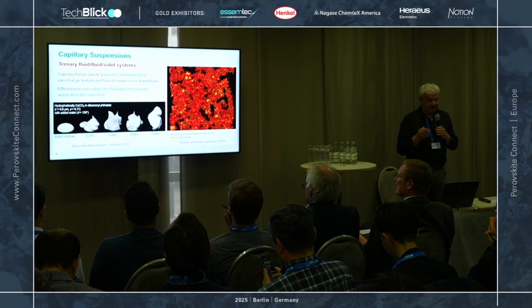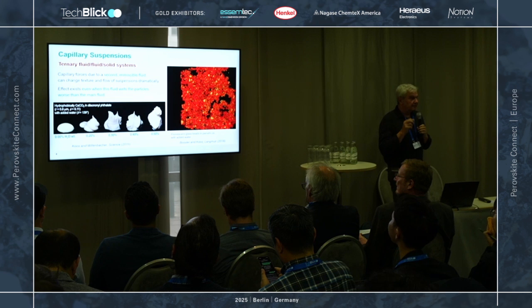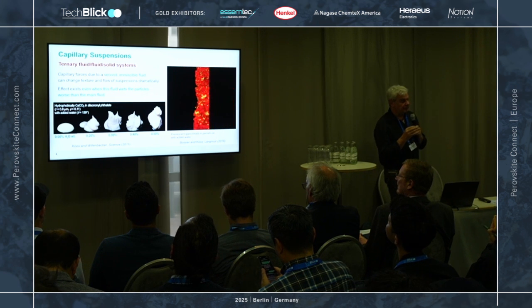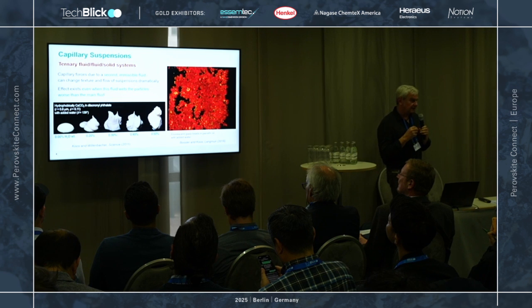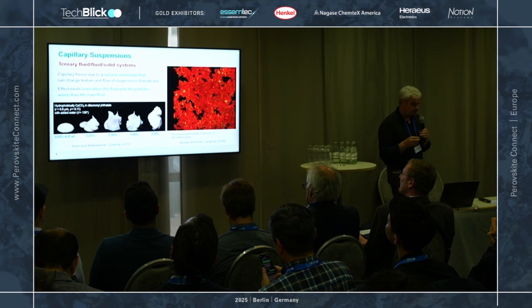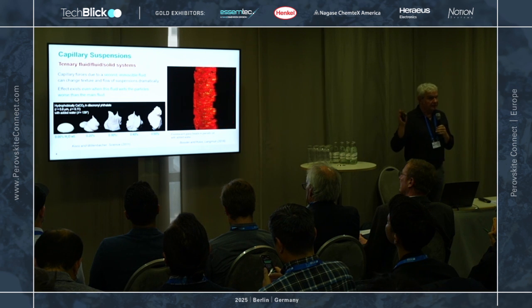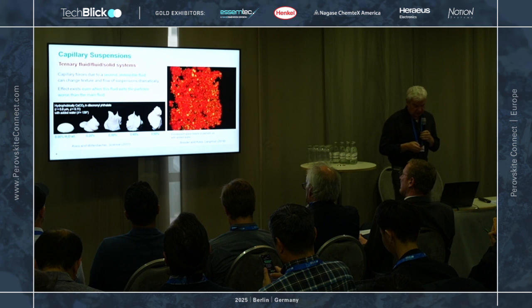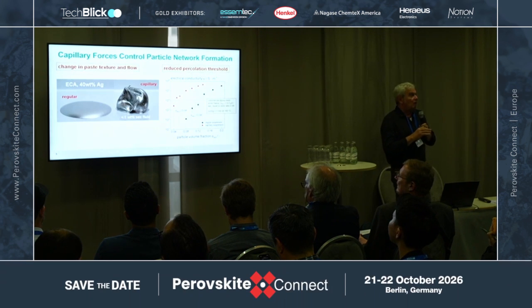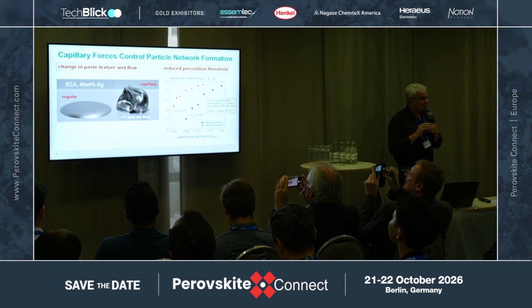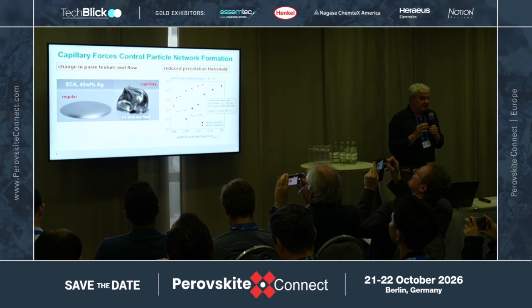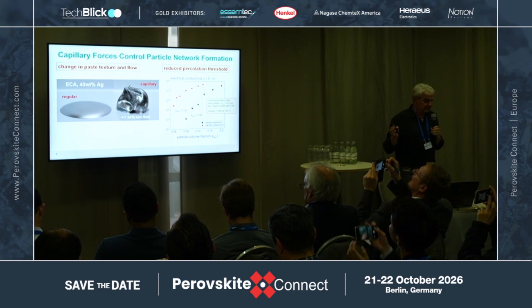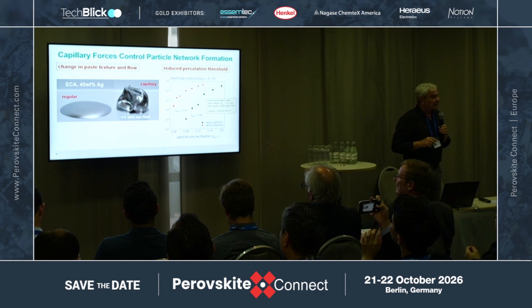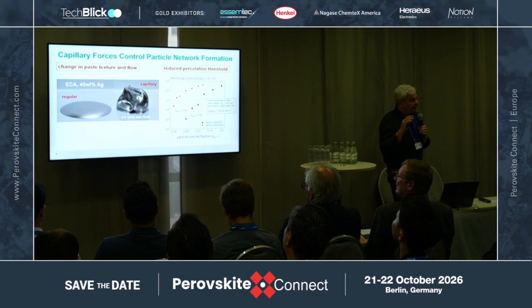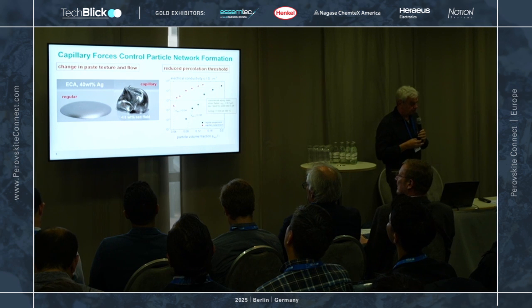And if you look at the microstructure, you see the secondary fluid, which is not miscible with the main fluid, sticks to the particles and induces the formation of a particle network. This has a dramatic effect on the texture, as you have seen in these images, but this applies to all kinds of suspensions of solid particles in two immiscible liquids, and it also works for ECAs, for instance. Here you see when you reduce the filler content, the silver content in an ECA, to 40%, you will have a freely flowing, nicely flowing resin system.